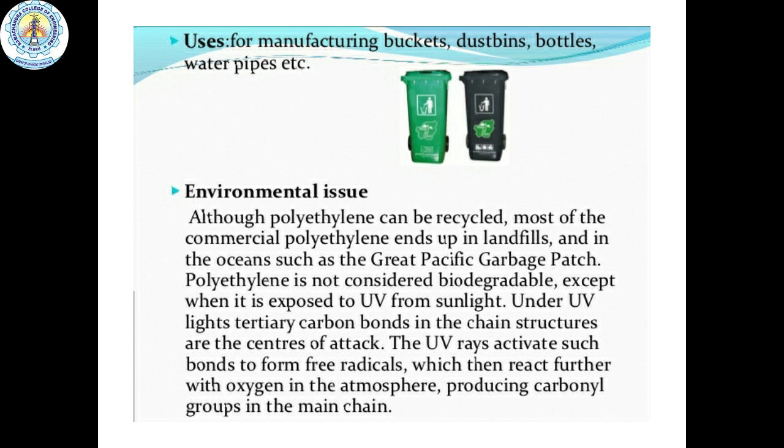Coming to the environmental issues faced by the polythene. Although polythene can be recycled, most of the commercial polythene ends up in landfills and in oceans, such as the Great Pacific Garbage Patch. Polythene is not considered biodegradable except when it is exposed to UV from sunlight. Under UV light, tertiary carbon bonds in the chain structure are the center of attack. The UV rays activate such bonds to form free radicals, which then react further with oxygen in the atmosphere, producing carbonyl groups in the main chain. This is about the polythene.